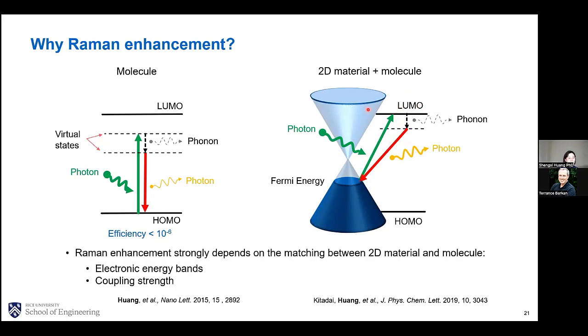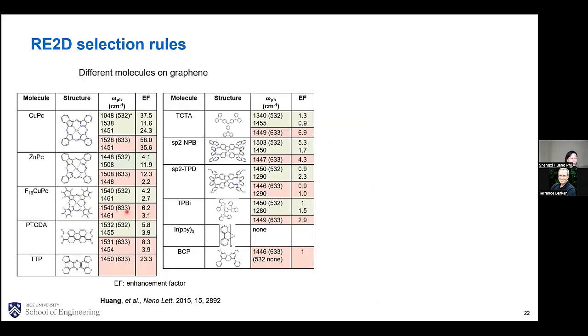So you can also see from this picture, the actual Raman enhancement will strongly depend on two factors. The first one is the electronic band alignment, and the second one is the coupling strength between the molecule and the 2D material. So these two factors actually constitute the so-called RE2D selection rules. Specifically, if we put different types of molecules on one type of 2D material, for example, on graphene, we can see the enhancement factors are actually very different from each other. You can see from this column here.